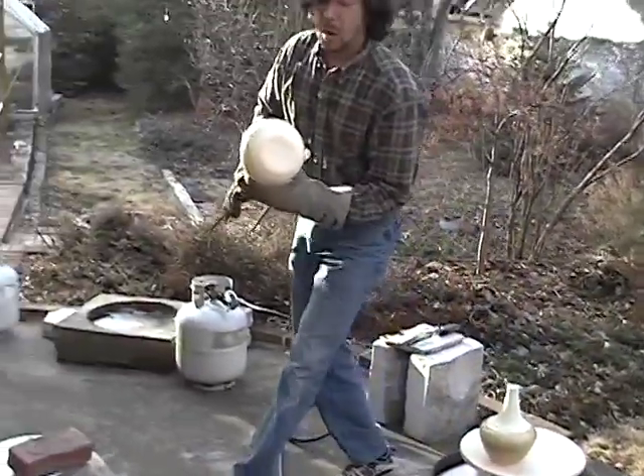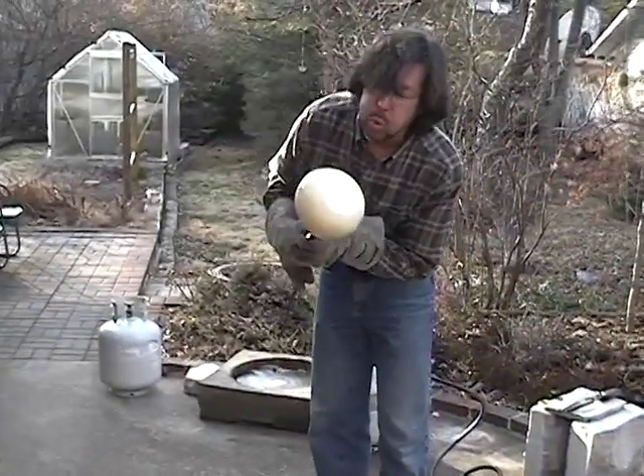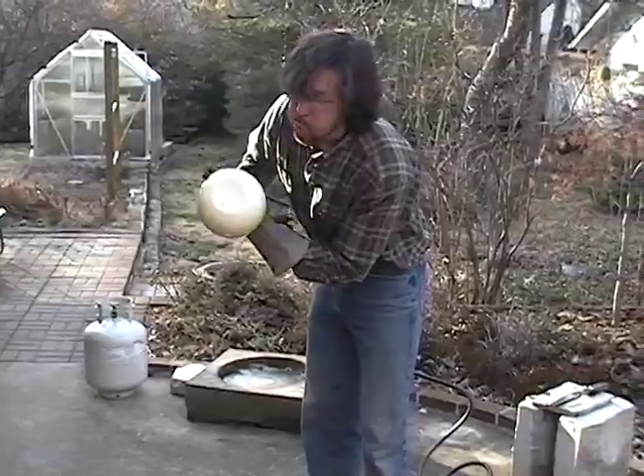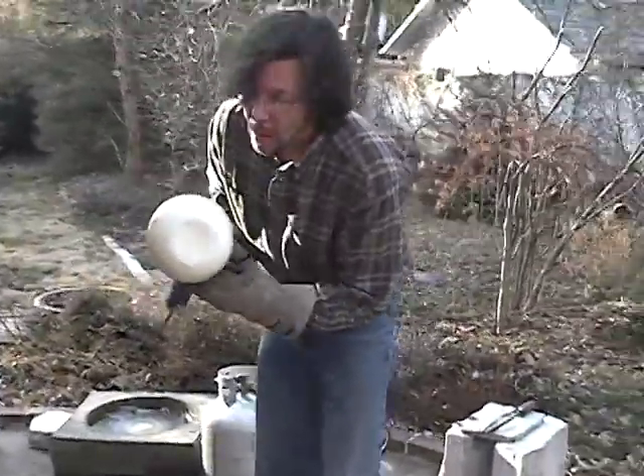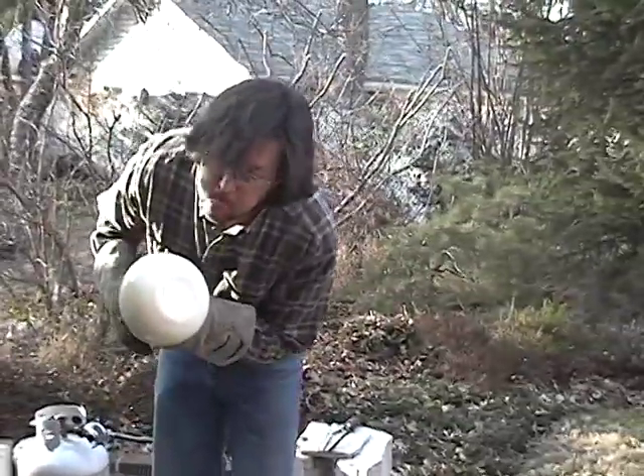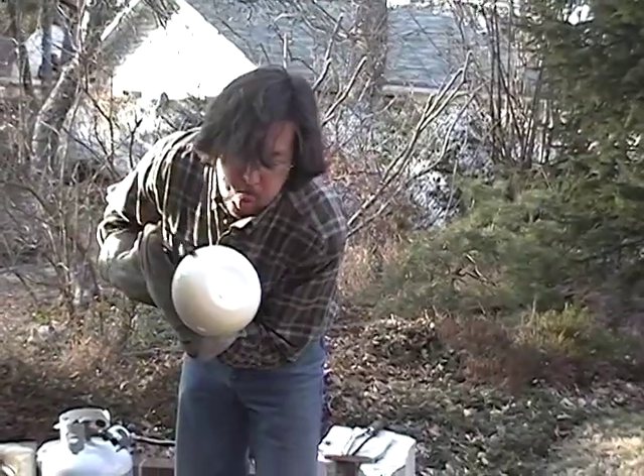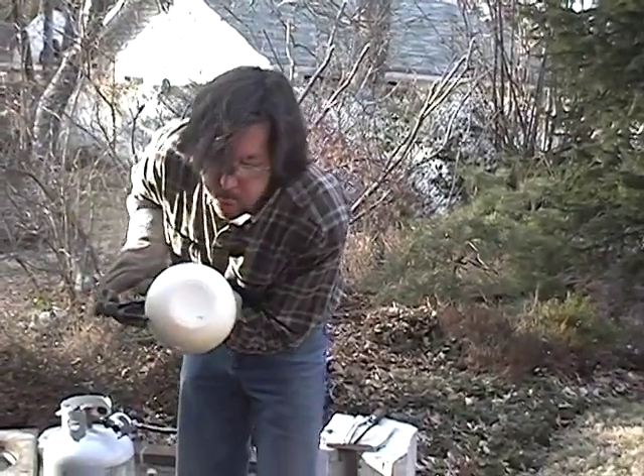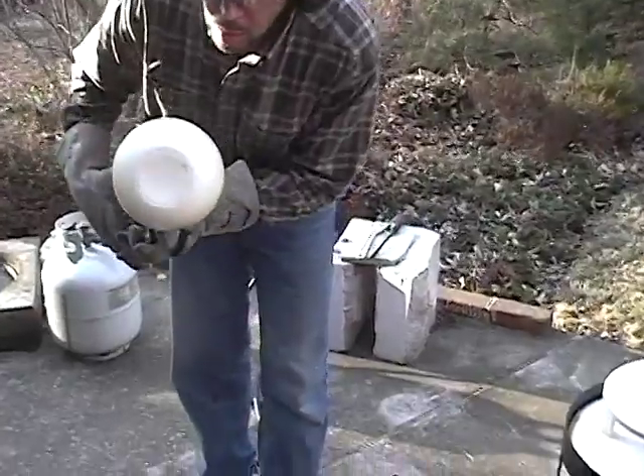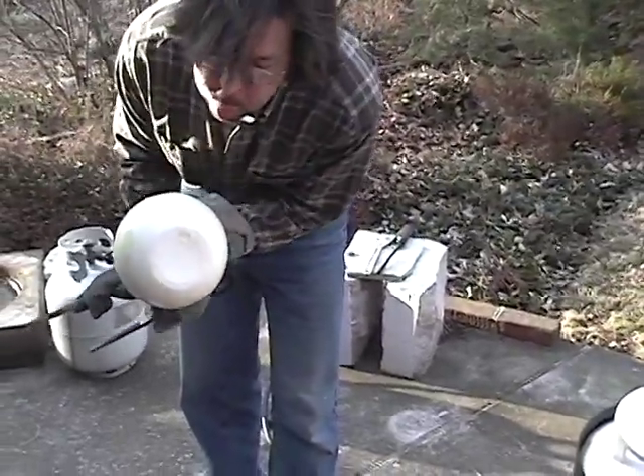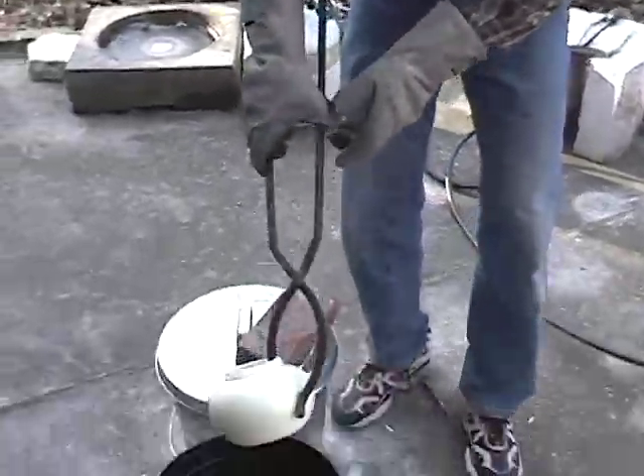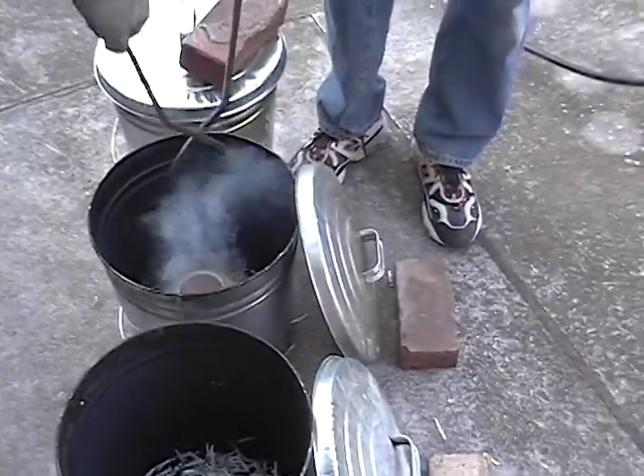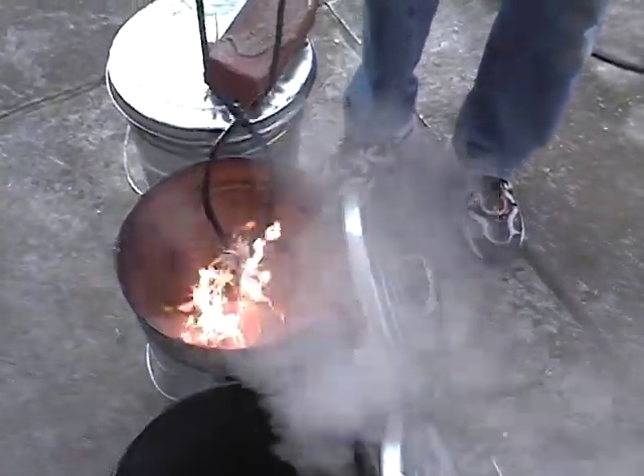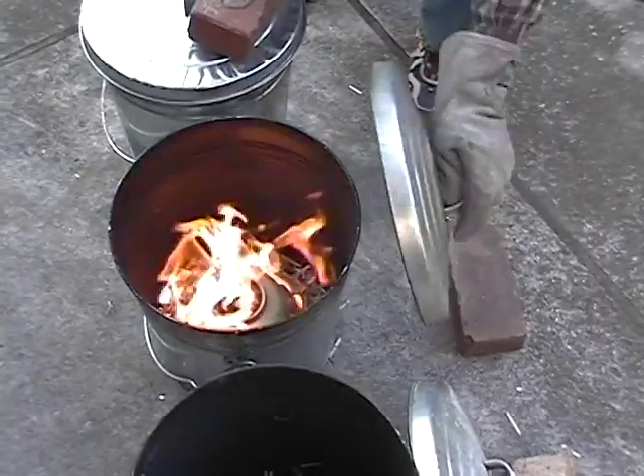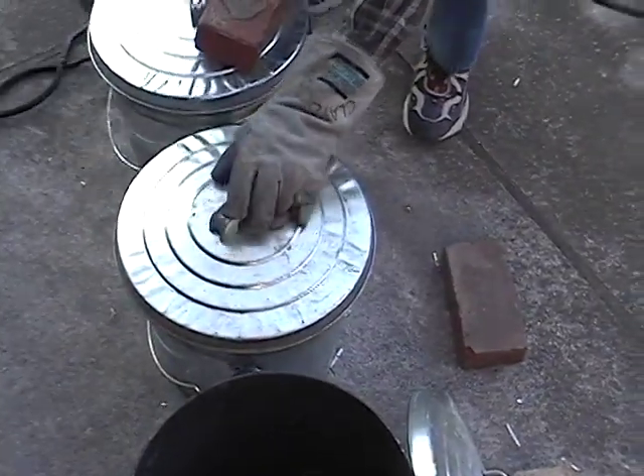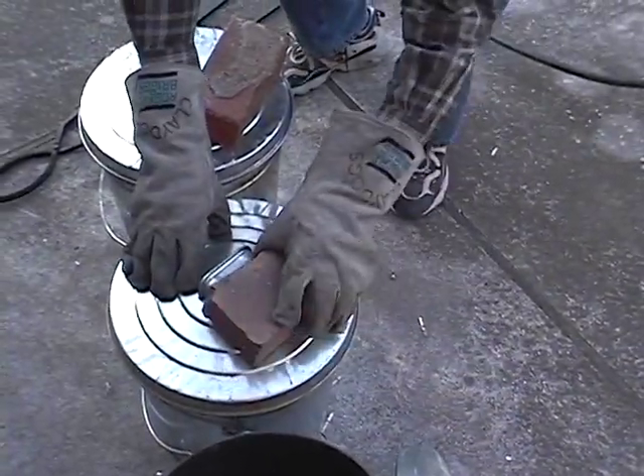On this particular piece we have a white crackle, and so we're going to blow on the outside of the piece until we actually hear the glaze start to fracture. It'll sound like little breaking glass. Once the piece has fractured enough, you can then take the piece and place it in the reduction media. This will give a nice even crackle across the surface of the pot. If the pot doesn't flare up, you can take some of the reduction media and toss it on top of it. Place on the lid and place the brick in place.